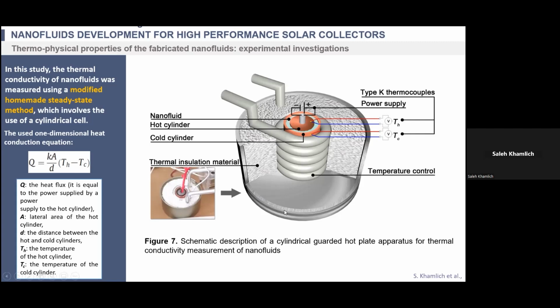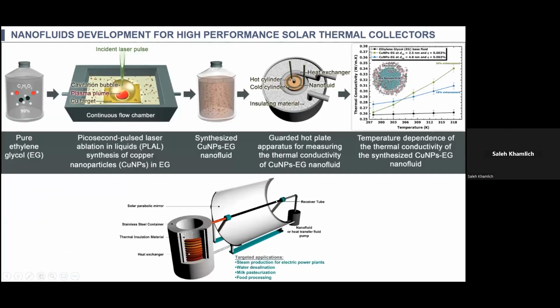Very simple, but it's a very robust method to find the thermal conductivity of nanofluids and liquids in general. So this is what we use to study the thermal performance of our nanofluids, after adding different types of nanoparticles, in terms of thermal conductivity, because thermal conductivity is a very important parameter in this technology. Very simply said, we start with pure ethylene glycol. We pump it through the chamber. We make the ablation. We create the nanoparticles. We have our nanofluid, and we test it.